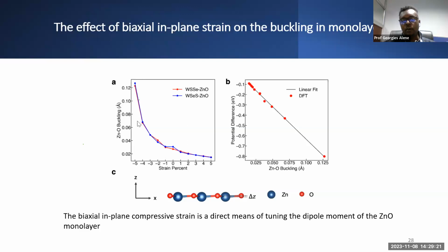So we are significantly changing the buckling of the zinc oxide by strain. But when we apply tensile strain, it is not significant, as you can see. The buckling reduced, but it is not significant. And we have seen also the potential difference, the dipole moment, and how it is affected by strain. So when you see here around 0.12 buckling, you can have like 0.8 electron volt potential difference. So we have learned that by applying strain, we can actually significantly change the dipole moment of the zinc oxide.